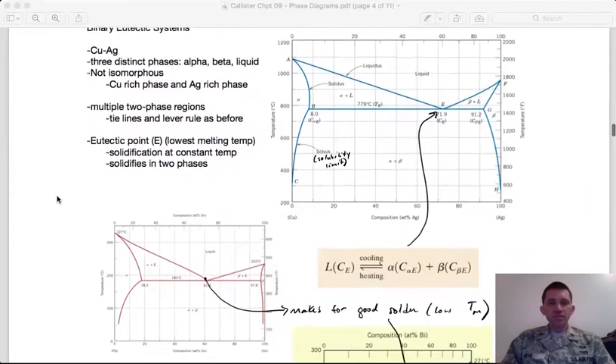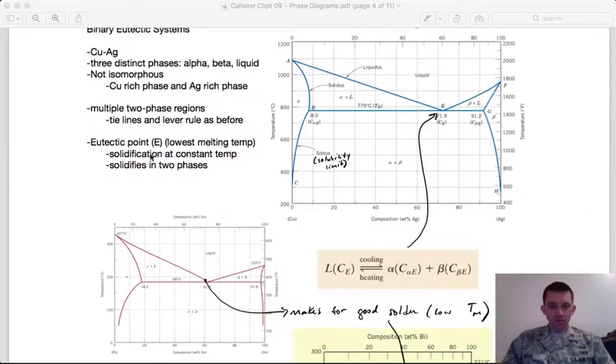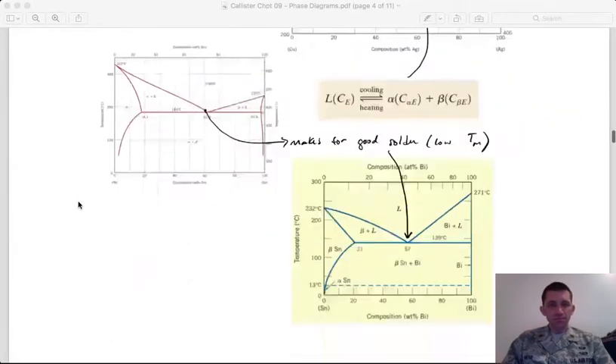But aside from those differences, we can think about this phase diagram in a similar way and use the tie lines and the lever rule just like we did before. The main addition here is the eutectic point. It's kind of similar to a triple point on a water phase diagram, but it's the point at which solidification occurs directly from 100% liquid to 100% solid. And when it does so, it solidifies directly from liquid into alpha and beta phase together. And it forms a distinctive structure that we'll talk about later.